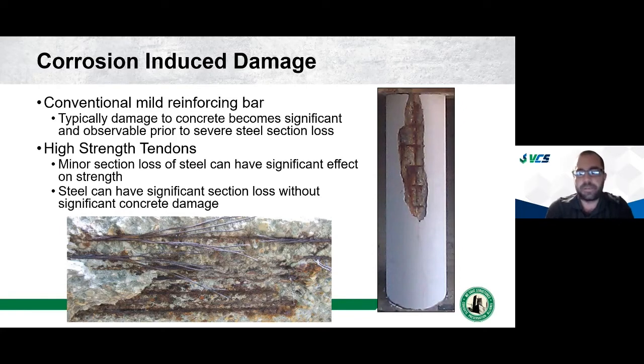Now, when we're looking at reinforced concrete structures, we've got to be careful to understand the difference between conventional and high strength strands or tendons. When we're looking at conventional reinforcing steel, on the right here, I have a column and you can see a spall. Typically damage becomes visually observable prior to significant structural capacity loss. We see some rust on the steel. We may only have 5–10% section loss on that steel to cause that spall. And that column, we're not concerned structurally for that column. That's something, okay, we see that corrosion is becoming a problem. We need to address it, but we're not worried structurally because the iron oxide has built up enough to cause some visual indicators, but that buildup hasn't caused significant section loss of the steel yet.